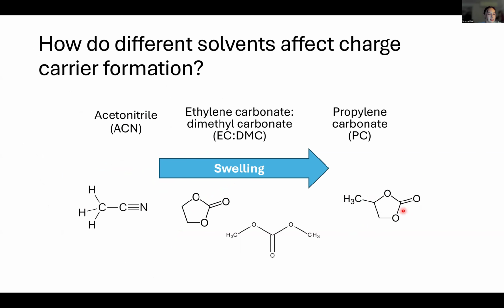So additionally, we're interested in the effect of solvent swelling, because when we are electrochemically doping, the solvent has favorable interactions with the hexyl chains, and then this causes swelling. So the 3 solvents we're interested in are acetonitrile, ethylene carbonate/dimethyl carbonate (EC/DMC), and propylene carbonate. And acetonitrile is not swelling, EC/DMC is moderately swelling, and propylene carbonate is our most swelling of the three.